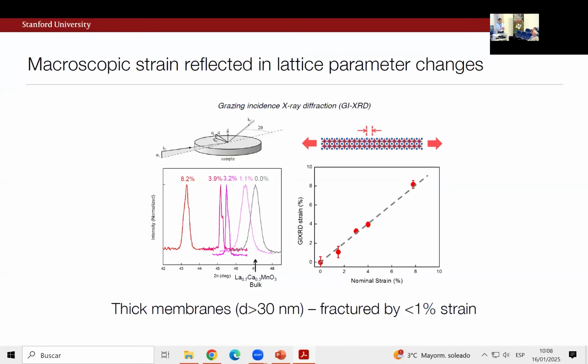Now, if you did this with a single crystal piece, right? When I was a grad student, I would play with single crystals of manganites. So believe me, you can't do this. And even by going on the scale of 30 nanometers or so thick in membrane, those statistics of fracture rapidly approach bulk values. So this thing drops below 1% of order. And so later on in this discussion, I'll tell you a little bit more about why that is possible and how to think about that.